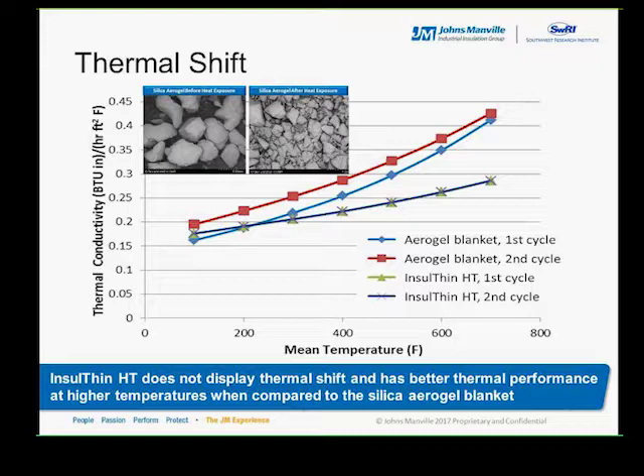The data shows that some of the thermal degradation seen in the previous slide can be partially explained by a thermal shift phenomenon that we've seen with silica aerogel blankets, but not the micropore-based blankets like Insulthin. To briefly summarize, exposing silica aerogels to high temperatures results in a degradation in aerogel structure and therefore thermal performance.